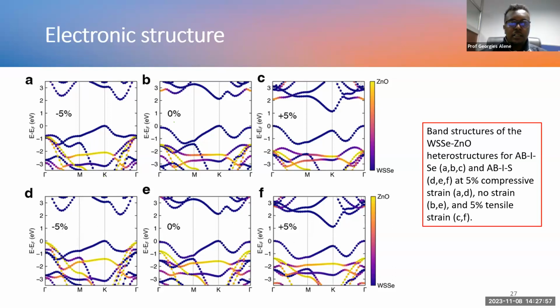And as you can see, you have a direct band gap semiconductor without strain. And it is almost, again, direct band gap with tensile strain. But when we go to compressive strain, it is like an indirect band gap semiconductor. So what we have learned from this investigation is that by applying strain, it is possible to change the band gap nature of the material and also the band gap alignment type.